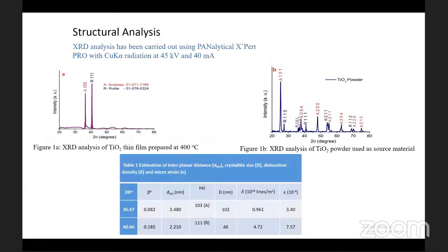The structural analysis. Figure 1A shows the XRD analysis of TiO2 thin film prepared at 400 degrees centigrade. Here it shows the signatures of the TiO2 thin film with two peaks only, whereas the source material, TiO2 powder, has mixed phases as well. Table 1 gives the estimation of interplanar distance, crystallite size, dislocation density, and microstrain.